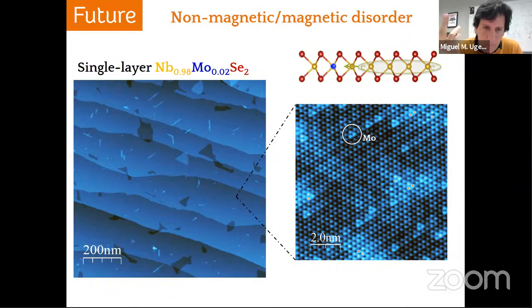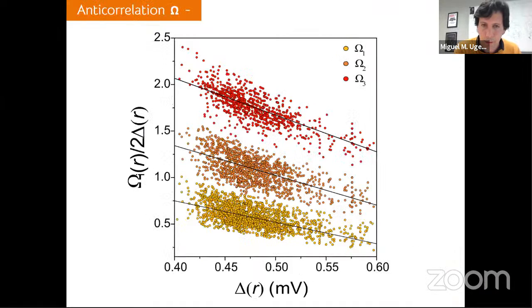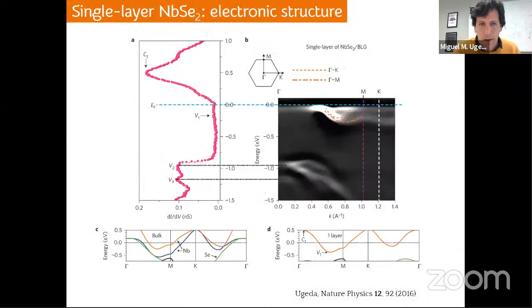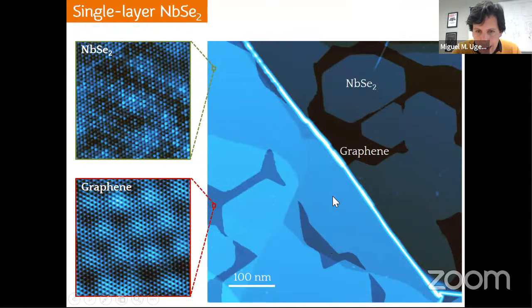It's true that we have also done part of this experiment on samples with lower coverage, and that leads to measurements in, for example, let me show you. Regions like, for example, like this, which is like half a micron size. But yet these regions are 5 times the coherence length of the material. So we don't think we are close to the confinement. In any case, we try to avoid measurements on small regions like this and like that for that reason. And in general, regardless of what you measure, you see the same features at the same energy. So I don't think confinement is an issue here. That's all I can tell you about it.